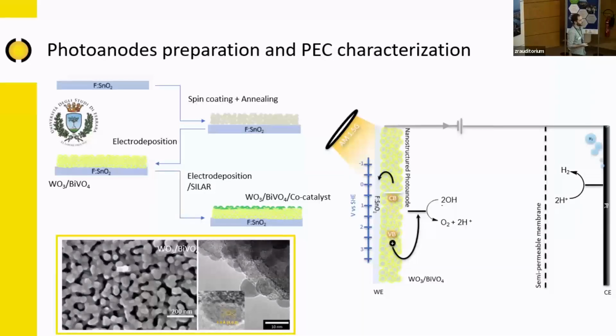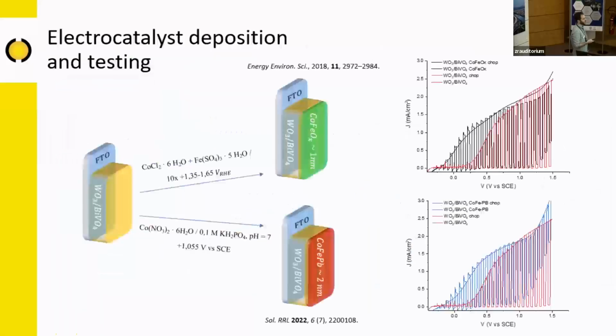And this is one of the most promising photoanode configurations, where we deposit a tungsten oxide nanoporous structure on a transparent conductive oxide, and then we coat this tungsten oxide layer with a bismuth vanadate layer that basically improves the light harvesting properties in the visible region, as tungsten oxide is not actually absorbing in the visible region. And then we can deposit different co-catalysts on the surface of this structure with different deposition methods. I'm not going to get too much into it. So the final photoelectrochemical cell looks something like this, where we're basically only interested in the oxidation reactions, or the oxygen evolution reaction performed by this photoanode upon illumination.